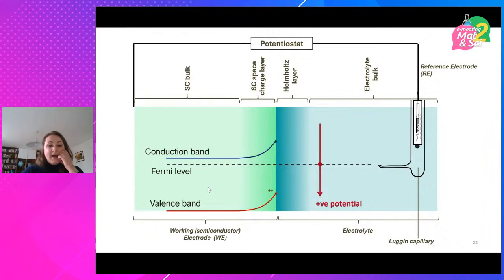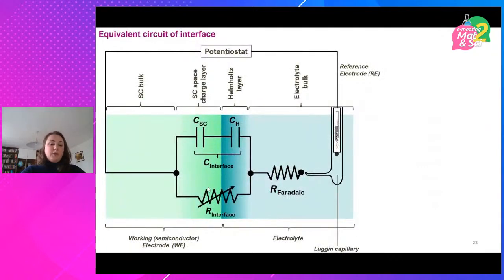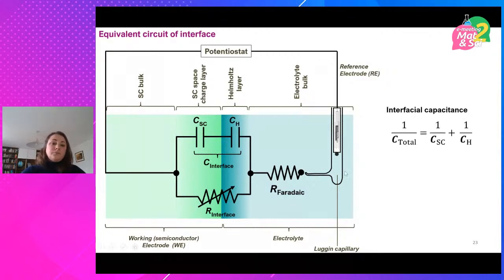And the question is, how do we probe what happens at the Helmholtz layer while this goes on? It cannot really be done without going through and modeling everything, because when you measure the overall capacitance of this interface, which is what you do with Mott-Schottky experiments, if you've ever determined the flat band potential, you've got two contributions to that. You've got the capacitance of the space charge layer and the capacitance of the Helmholtz layer. Everybody always assumes that the capacitance of the Helmholtz layer is so much larger than the capacitance of the semiconductor that it's completely irrelevant to the measurements. But what has become clear through the modeling is that that's not the case for highly doped semiconductors.